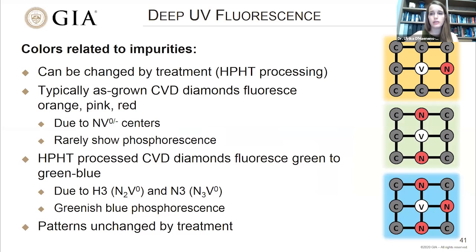A lot of CVD diamonds, when they're grown, originally have this quite unappealing brownish tinge to them. By HPHT processing, they're able to remove the defects responsible for that brown color and end up with a much more valuable colorless material. It's similar to the HPHT treatment that exists for some natural diamonds as well.